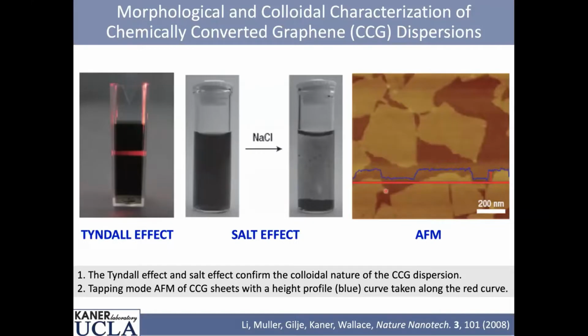So if we look at atomic force microscope of the pieces that come out, if we run a trace along here, you'll see about a 1 nanometer step height. And people have decided that's graphene.